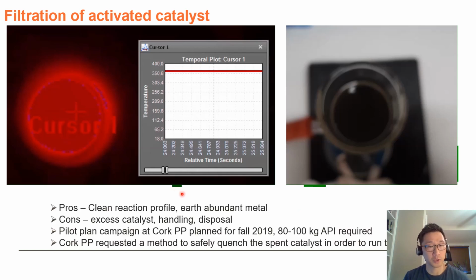So the pro of using Raney cobalt is that it gives us a very clean reaction profile using an earth-abundant metal. The con is that because we're loading 10 to 28% catalyst, that's a lot of catalyst that we have to handle and dispose of later. Now, we had a pilot plant campaign planned at our Cork pilot plant where we anticipated making about 100 kilograms of API. You can imagine if we're charging 10 to 28% catalyst, that's 20 kilograms of catalyst or so.